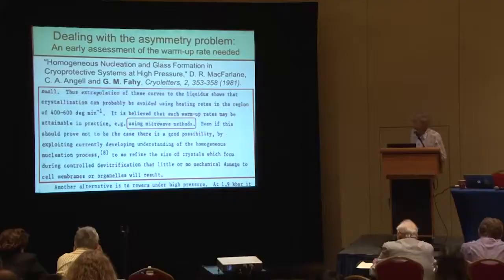So as we heard from Brian Work yesterday, you need to adjust your frequency of radiation if you want to excite the molecules and dissipate the electrical field energy at temperatures which are not in the peak, where the relaxation time is not in the microwave range. So this particular speculation about microwave methods is not exactly the best one, but it was at least recognizing the idea that you had to do something.